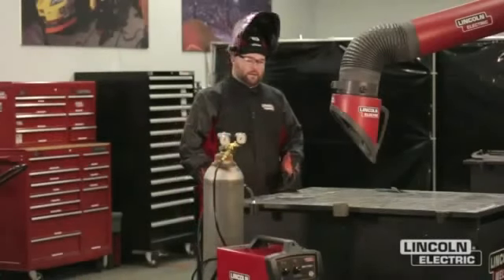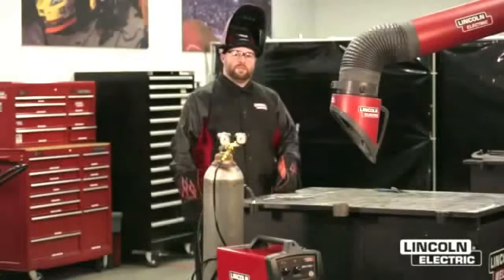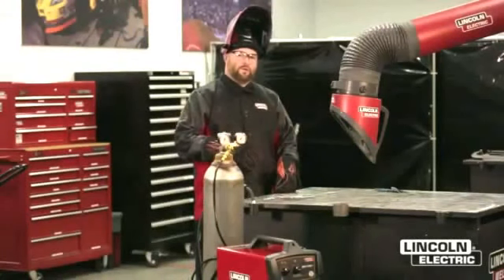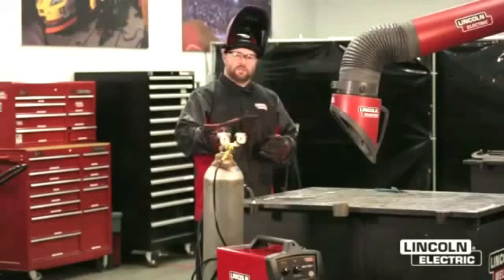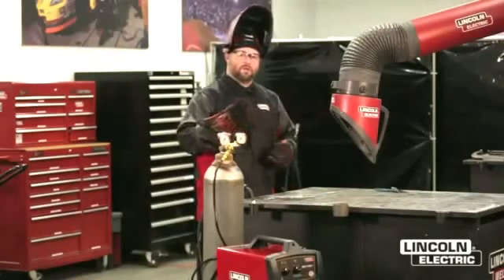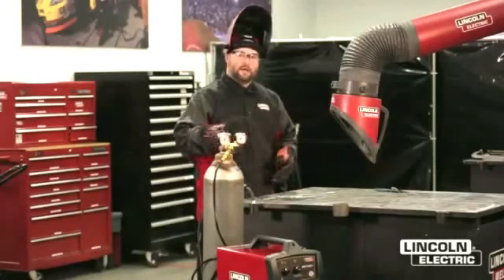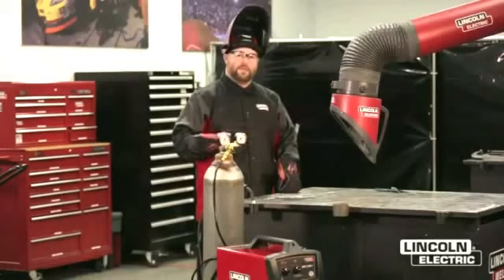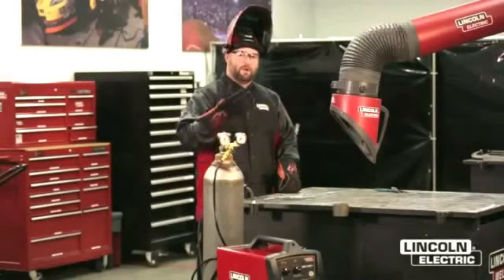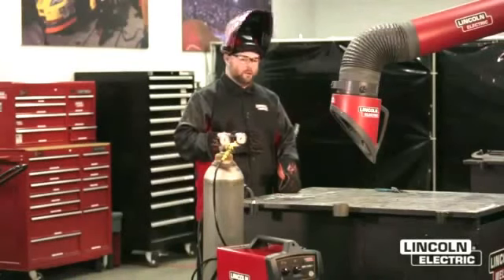The next weld we're going to make, we're going to have our wire feed speed too low. Now when we have our wire feed speed too low, you're going to start to see large droplets coming across the arc. So when we see that, we need to go back and make an adjustment and either turn our wire feed speed up or turn our voltage down.